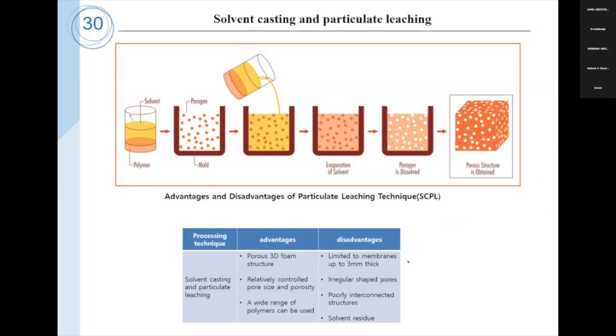However, this technique has some disadvantages. It can only produce membrane type scaffolds, with a thickness of about 3 mm. It also gives irregularly shaped pores, because the salt porogens are not regularly shaped, and a poorly interconnected network structure. And sometimes, once we evaporate the solvent, residual solvent is still present that can affect cell growth, cell proliferation, and differentiation. So this technique has some advantages and disadvantages.